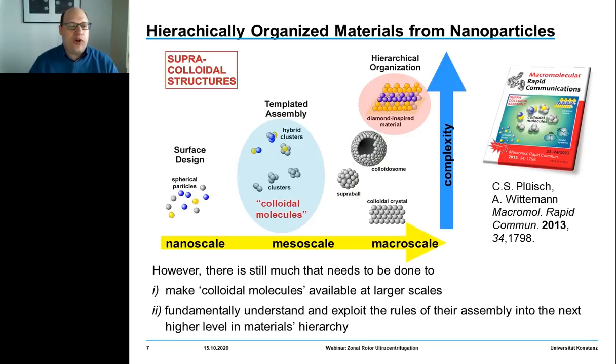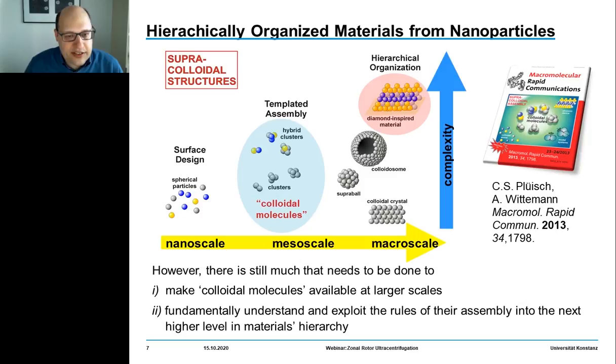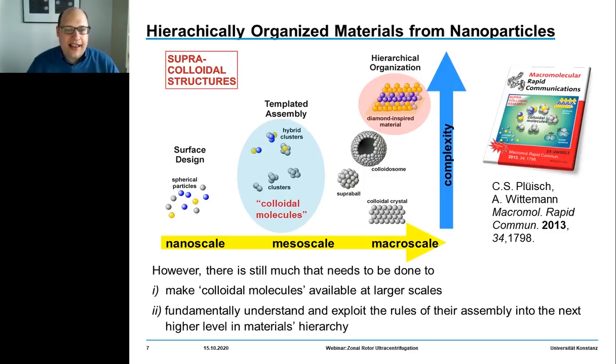These colloidal molecules take on a key role in supracolloidal assembly, as they have the potential to bridge the gap between single particles at the nanoscale and highly complex materials. For example, this is a colloidal tetrastack — an assembly of tetrahedral shaped particles — often considered the holy grail of a photonic material, as it provides large and robust optical band gaps across the full range of visible light.